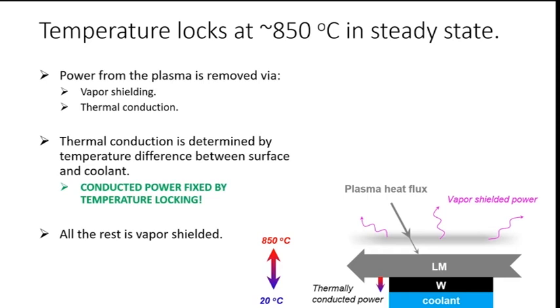And then maybe a final note on the question why. Why do we have this locking at 850 degrees Celsius? And the answer here lies in the mechanics of evaporation, more or less. So evaporation is a temperature-dependent process, and it goes as a very strong function of temperature. So even the slightest few degrees of temperature increase will give you a very large increase in evaporated particles. And because of that, you only need a very small temperature increase to have a lot more vapor